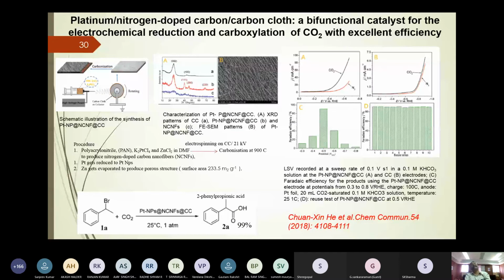Now the next slide shows how platinum nanoparticles are deposited on nitrogen doped carbon cloth. So it is a bifunctional catalyst for the conversion of CO2. Here they have made this platinum doped nitrogen carbon cloth by a simple process called carbonization. There they use polyacrylonitrile, chloroplatinic acid, and then zinc chloride in DMF. They use electrospinning on the carbon cloth by using 21 kilovolts.